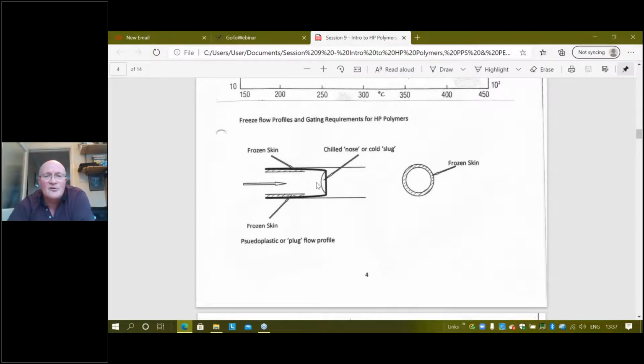And that will be forced all the way through the molding. Particularly with PEEK moldings, you'll often find great difficulty in knitting weld lines the further you are away from the gate. Quite often that is due to melt temperature loss during the first stage injection pressure. So you need to get to about 98% cavity shot weight on the first stage as fast as possible to maintain the melt temperature, because PEEK loses heat rapidly as you're filling the tool.